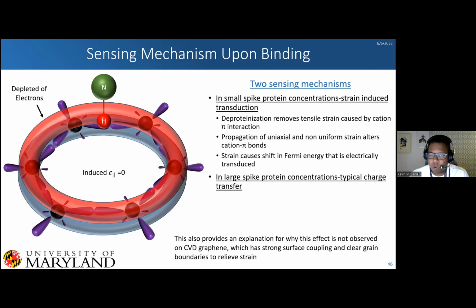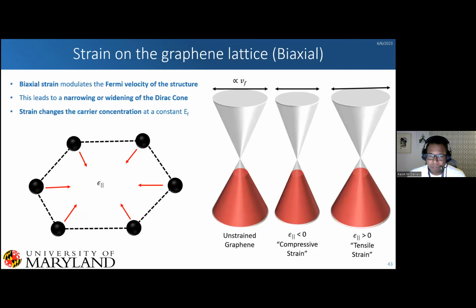And so what we're proposing is two sensing mechanisms. One where we have a small spike protein concentration. This causes deprotonation. It removes tensile strain caused by the cation-pi interaction. And then we have a propagation of uniaxial non-uniform strain altering these cation-pi bonds. And this causes a shift in the Fermi energy that we can electrically transduce. And then when we get into higher concentrations, of course, we have the typical charge transfer that everyone has observed.